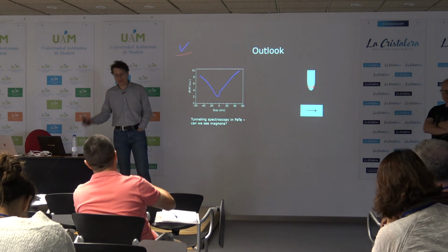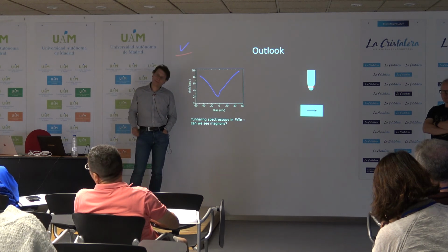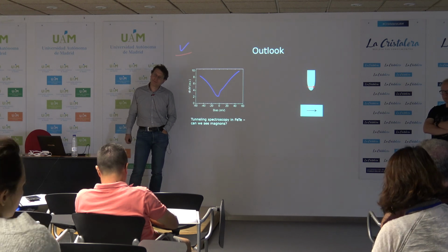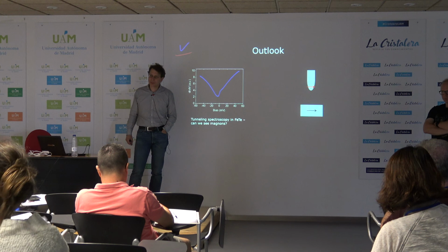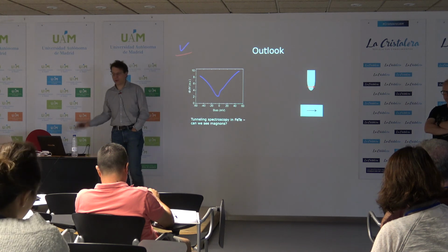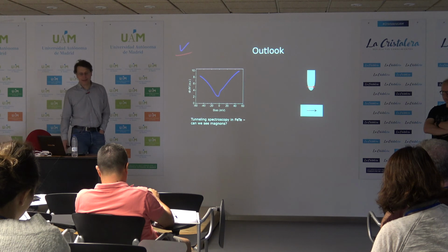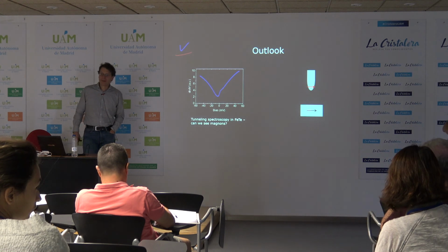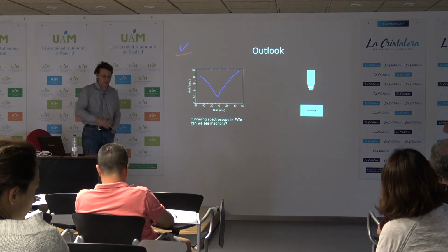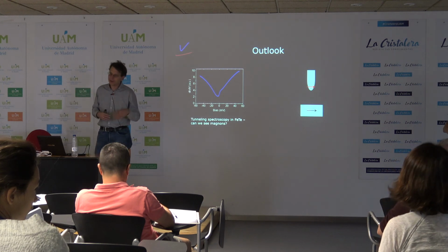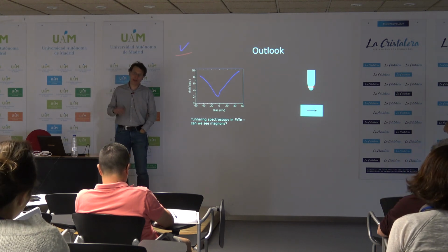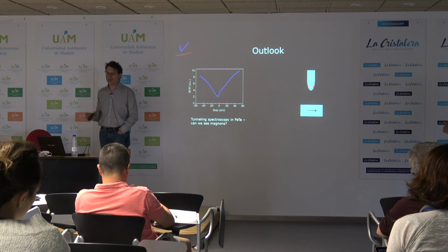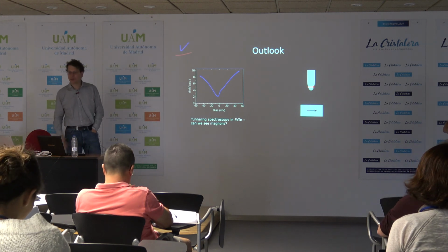But obviously, from sample to sample, one has to check that. If you just have an iron atom, that one does change with the field. Yeah, that does change. That's good. Well, if it's paramagnetic, you won't see any magnetic contrast without the field. And if you have a cluster, typically even for small fields, it will follow. But in these studies, we've used fields where we are sure that it will follow, so a few Tesla. But for a properly ferromagnetic tip, much smaller fields are sufficient. If you want to study, for example, these 2D ferromagnets, one has to use lower fields, because otherwise the sample just follows.